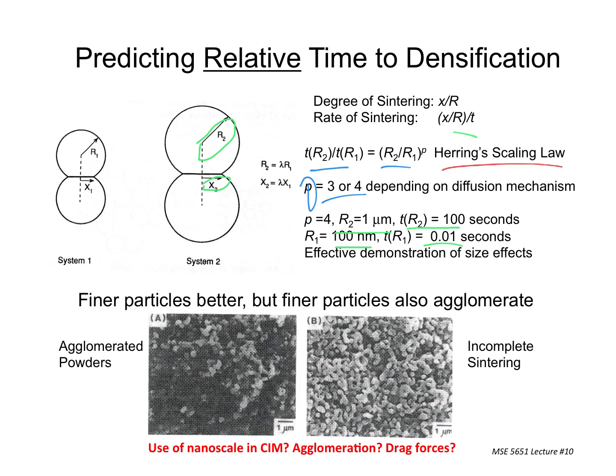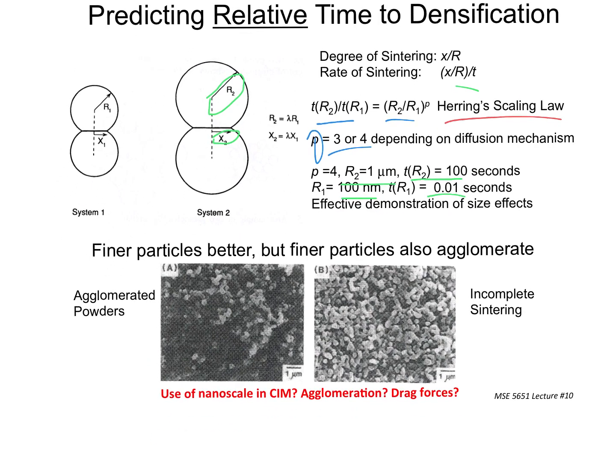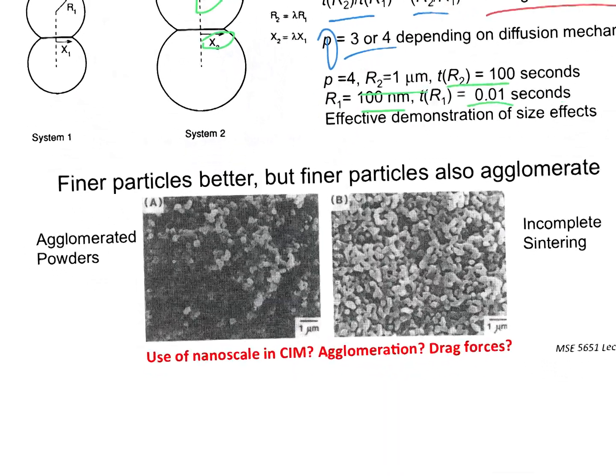And so when R is small, and you saw this in that hot stage microscopy video, if you look closely, it's all at the beginning. When you start with these initially small particles, they almost disappear instantly, and you see grains show up that are way bigger than the original particles. So the small particles grow almost instantly and become larger particles, and then the rate of change slows down a lot because the particle size is now larger.